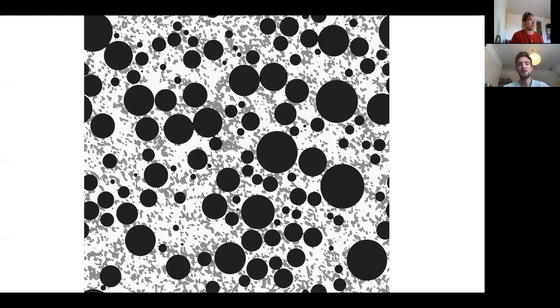Other limitations, there are particular limitations around geometry. So for example, it's really hard to make perfect circles. And that's an issue with long range dependencies. It's hard for one side of a circle to talk very coherently to the other side of a circle and say, we need to be perfectly round with this curvature. So those are two of the key limitations we've come across: long range features and resolution, which is just a computational limit, which we'll get around eventually.